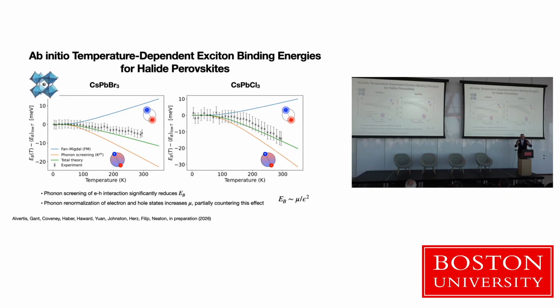So essentially, to take a step back really quickly and think about the hydrogen atom, phonons tend to localize the electron and hole, increase the effective mass, increase the binding energy, but the electron-hole interaction is also screened by the phonons, and that screening dominates in this system, and that gives rise to this reduction in the binding energy. So this is a work we're preparing.